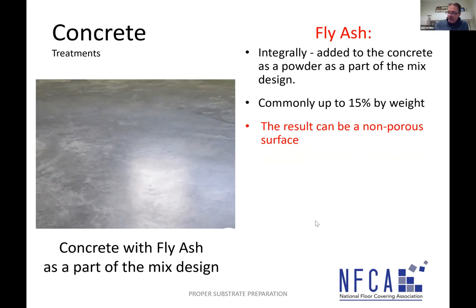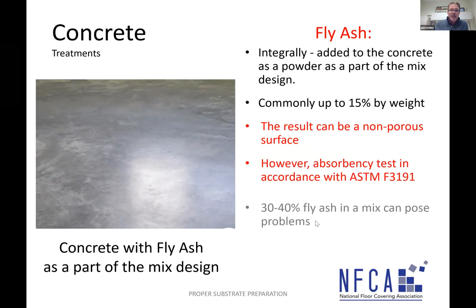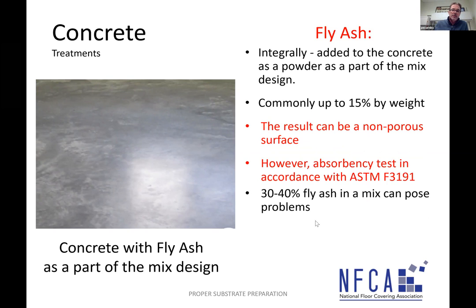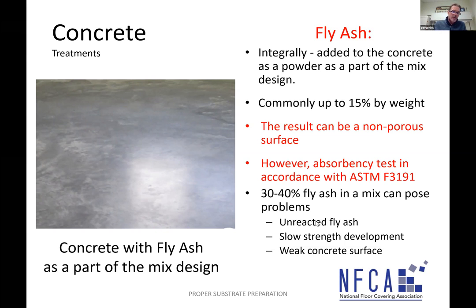there can be fly ash concrete that has some very high percentages, up into the 30 and 40% range, okay? And it can create a surface that's really non-absorbent. And we got to look at doing the absorbency test again to see whether that concrete's absorbent, okay? But when we get up to these high levels, 30%, 40%, I mean, there can be some problems. There could be unreacted fly ash in that mix, because remember, the fly ash is not reacting with the water. The fly ash is reacting with the byproduct of the concrete chemistry, that lime that's in there, that calcium hydroxide that's in there. And there's only a certain amount of free lime in the concrete for it to react with. There can be slow strength development, which also could possibly create a little bit of a weak surface.